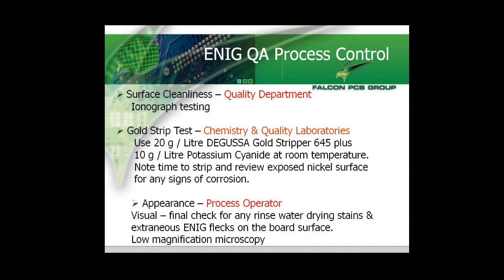And when we strip it, we can look at the gold surface and review the nickel just to make sure there are no signs of corrosion. The process operator will also check for any rinse water drying stains or extraneous electroless nickel immersion gold flecks on the board surface using low magnification microscopy.